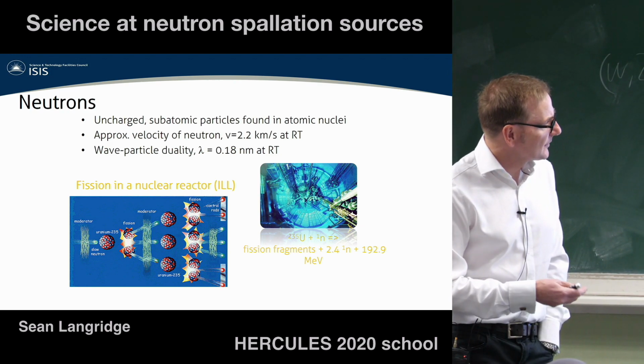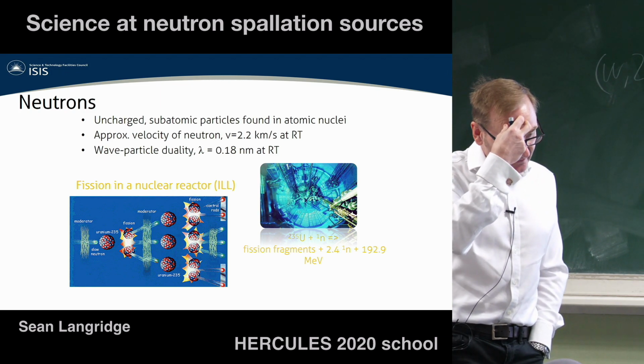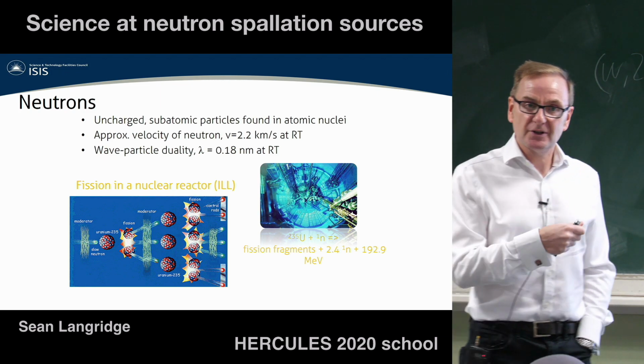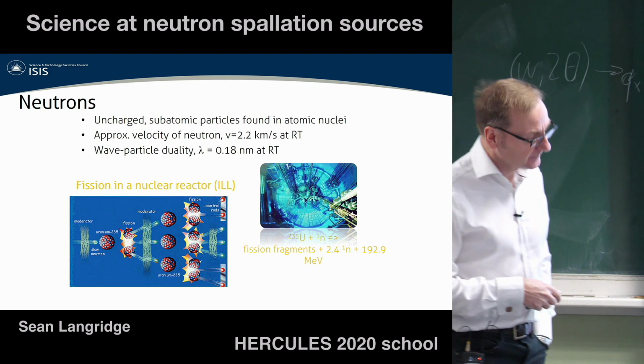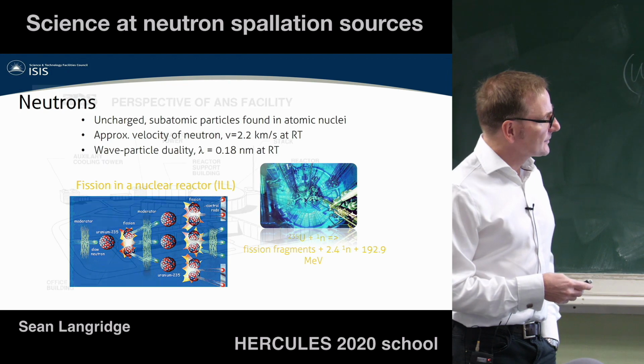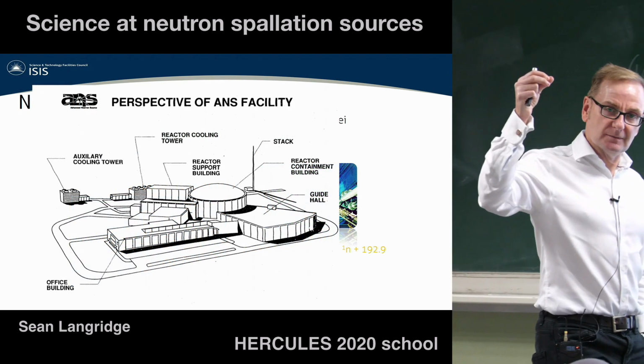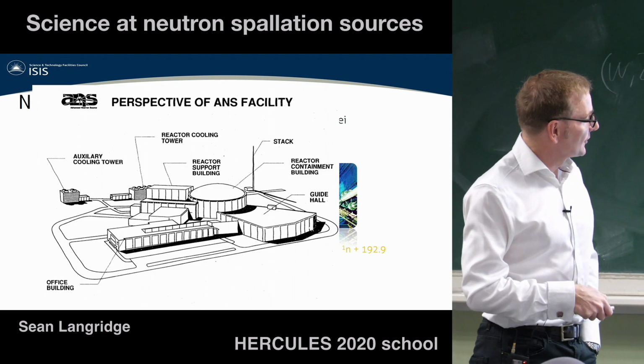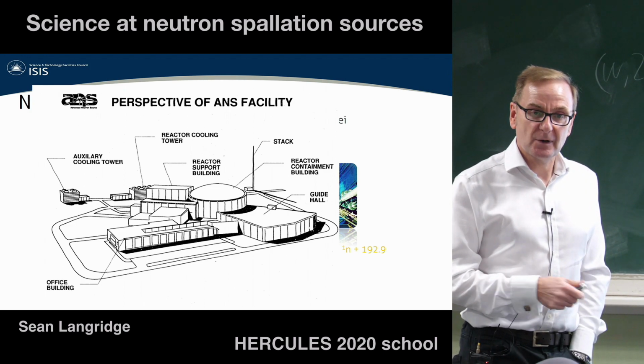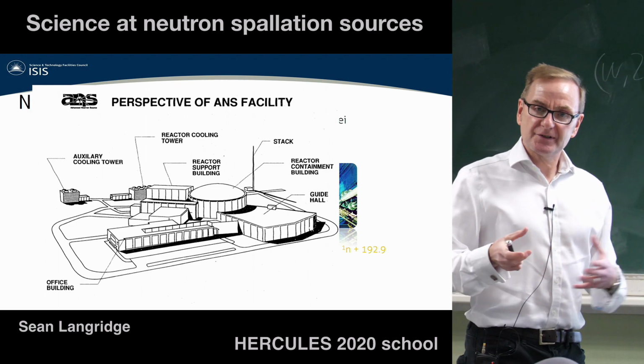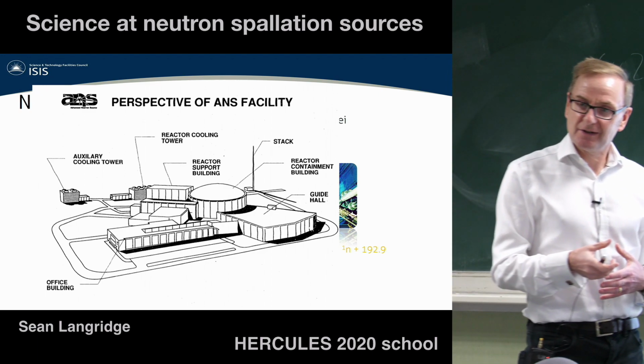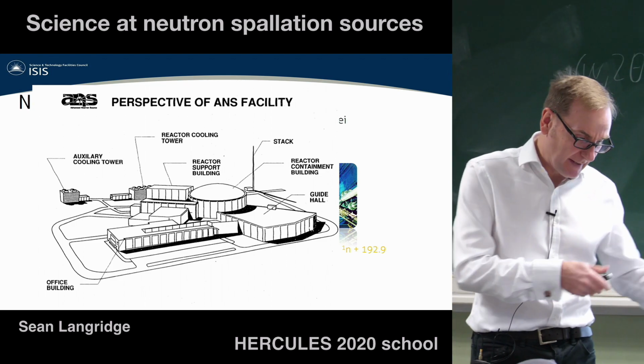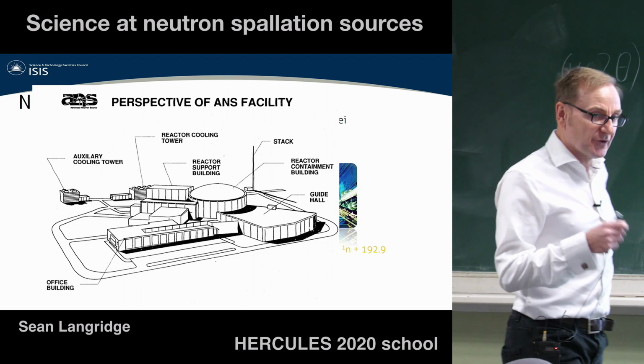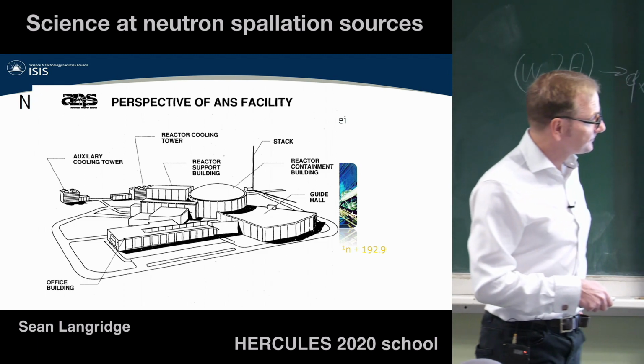So typically at the ILL, when it was running, I'm old enough to remember it was running at 58 megawatts, you'd have something like 10 to the 15 neutrons per square centimetre per second. But the ILL is almost certainly the pinnacle of what we can achieve with reactor sources. This is an old image that I found of the Advanced Neutron Source, which is a proposal in America. So the kind of supremacy in neutron science has moved across the Atlantic at different periods of time. And this is part of the Americans' response to try and move the centre of mass from Europe back to the US, which is a proposal for a 350 megawatt source.